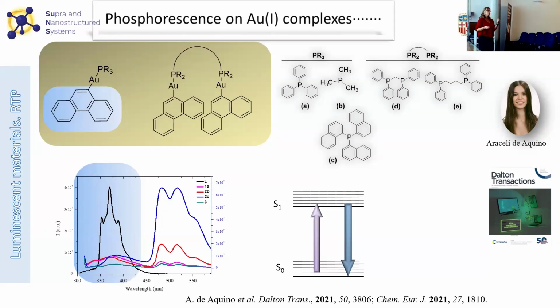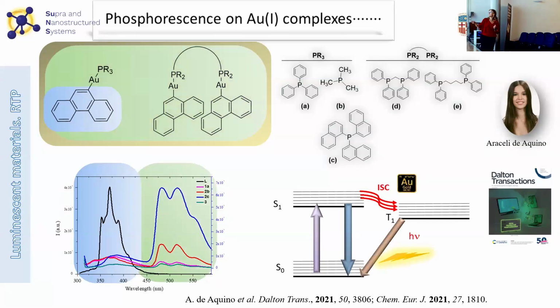But what happens if this chromophore is directly coordinated to the metal center? What we can observe is that, in fact, this intersystem crossing is favored, and we can have this room temperature phosphorescence emission. So this is reflected here in the emission spectra, since this one is decreasing in intensity, and what we have is mainly this band at longer wavelengths, that is due to the phosphorescence. So we can play with the luminescence just by introduction of a heavy metal in the chemical structure.